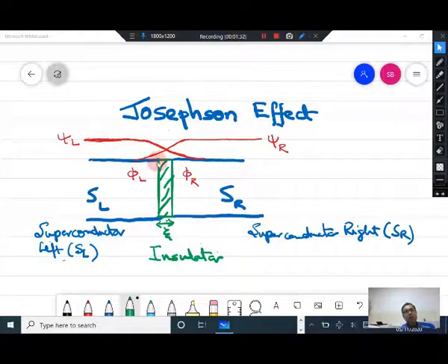But as you approach the superconducting interface, a little bit of the Cooper pairs will tunnel into the interface region and enter the right region from the left side, and similarly from the right end across the interface, a little bit of the Cooper pairs will tunnel across and enter into the left region. The interface is no longer a sharp boundary, but the Ginzburg-Landau equation has shown you that the superconducting order parameter decays over the coherence length xi.